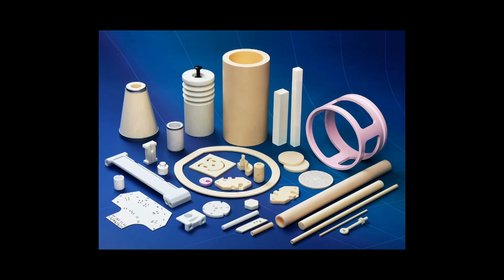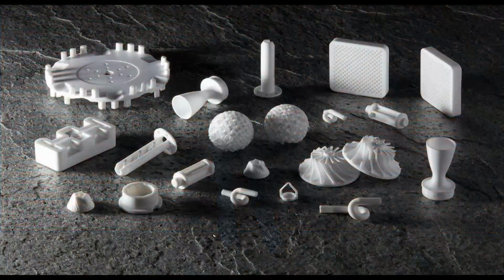So you might be asking, why aren't there more ceramics in the world? They have these amazing properties. And there's this concept in the technical ceramics world that nobody ever wants to use a ceramic, but sometimes you have to. And that's because it's very difficult to shape. Those amazing properties also mean it's very difficult to shape. It's very high temperature, so it's hard to melt, and very hard, so it's hard to cut. And so if you look at typical ceramic parts in the world, these are not ours, they often have fairly simple shapes because you're limited in your ability to shape those materials. But if you look at 3D printed ceramics, you can bring total flexibility in shape to this amazing material. And we're really excited to do that with alumina.